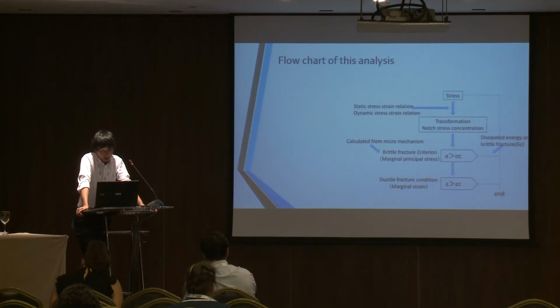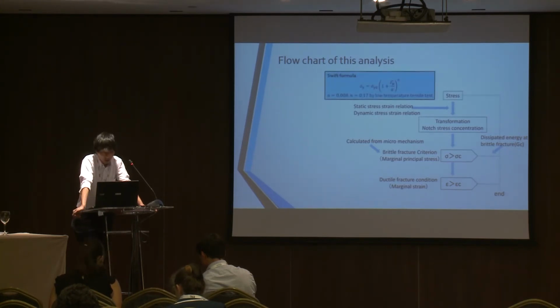Regarding the static stress-strain relationship, a low temperature tensile test was carried out, and fitting was performed using the Swift equation. Regarding the dynamic stress-strain relationship, the Cowper-Symonds equation was used for fitting, but in actual experiments, the results were scattered, so fitting is based on values from the literature.